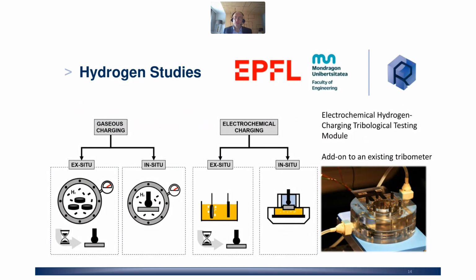So the idea is that for this kind of hydrogen study, you would still have the application where you charge the material under hydrogen at high pressure, then try to do in situ measurements under high pressure. But here the idea is really to have a setup of electrochemical charging and to be able, at the same time or just after, to do tribological tests. This cell is relatively small in size and has the advantage of being installed on a standard tribometer to do advanced studies. So I'll show you a little bit of the application of hydrogen on an existing tribometer.